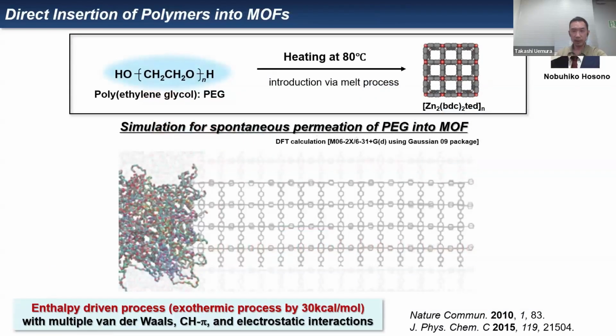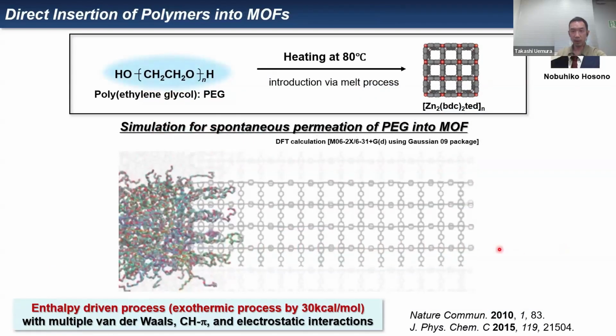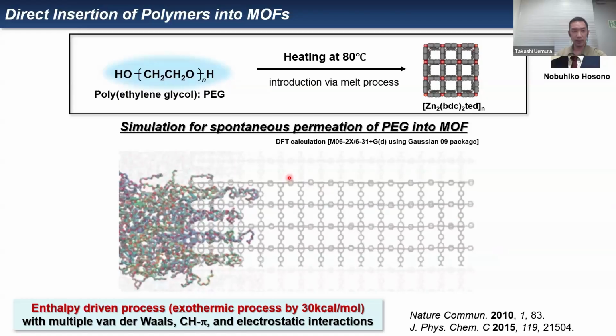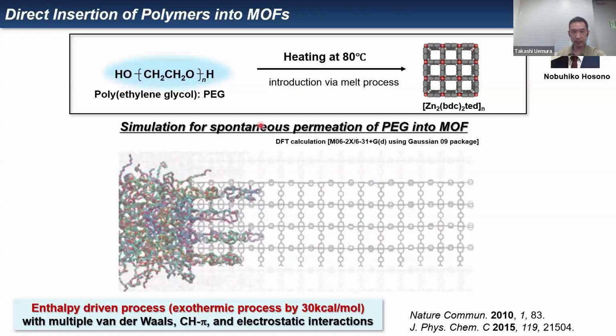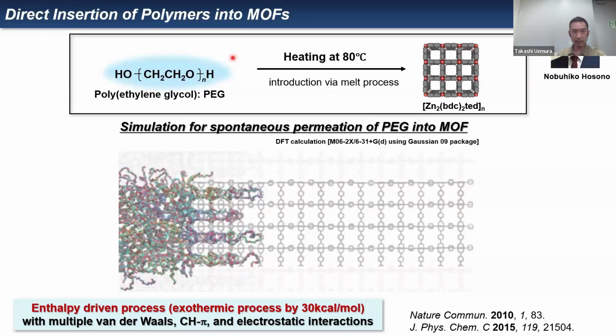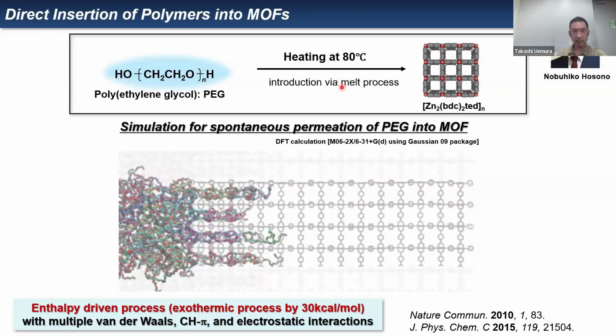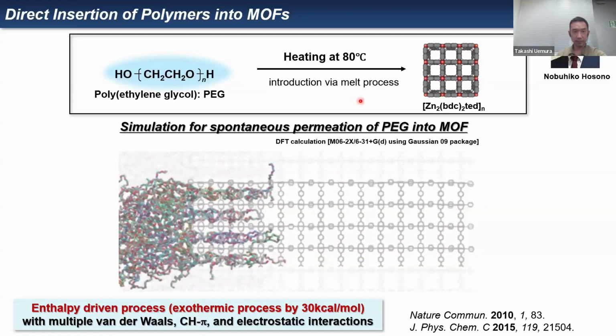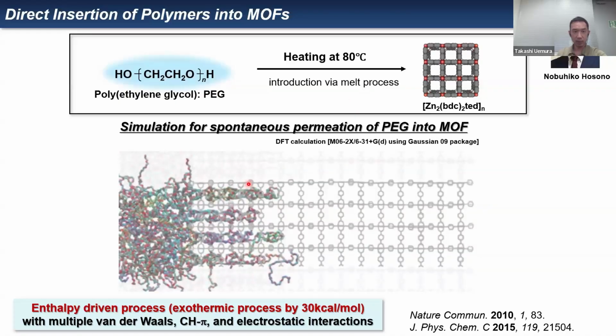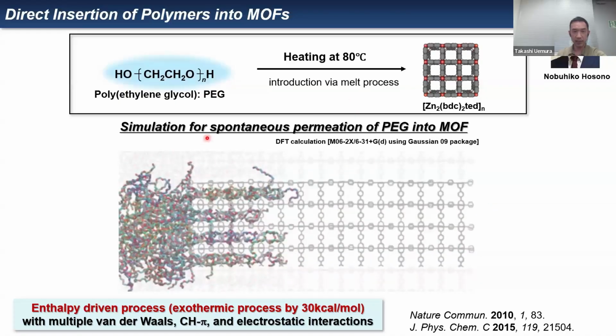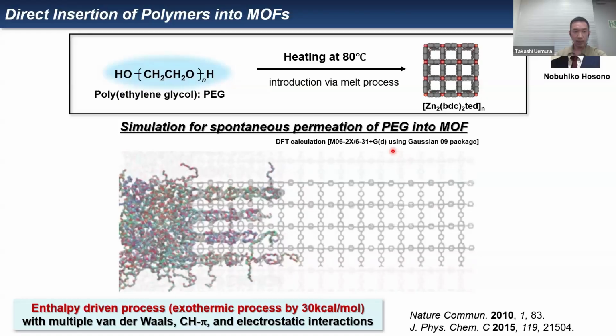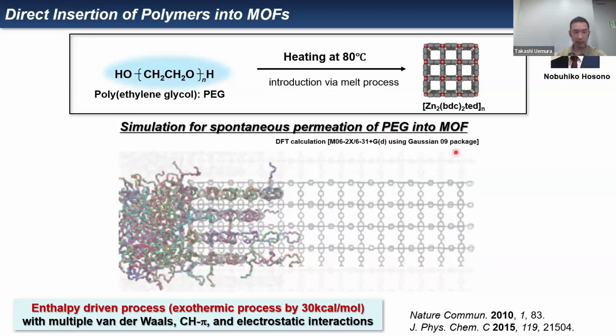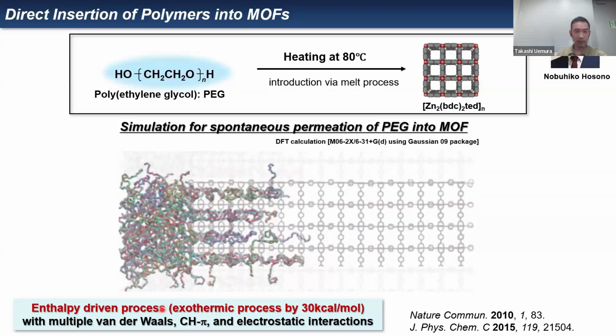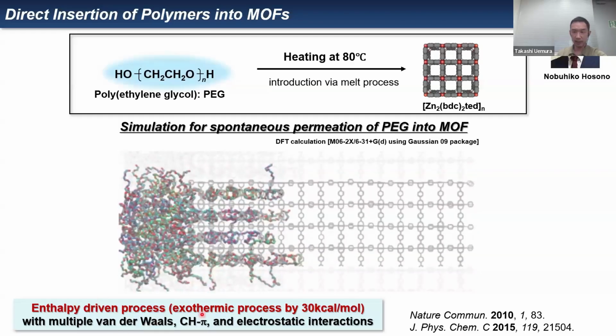But MOFs can do it. We could directly introduce polyethylene glycol, PEG, just by heating above the melting temperature, by a melting process. Here you can see the simulation of the spontaneous permeation of PEG chains into the MOFs, which is an enthalpy-driven process with multiple van der Waals, CH-pi, and electrostatic interactions.